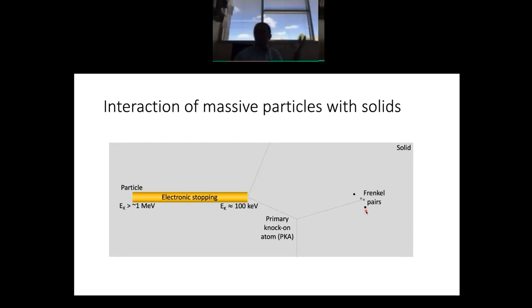And if I just think about what happens next, well, these things are just going to diffuse around, right? So they're just going to move around. Occasionally, you'll get a vacancy meeting up with an interstitial and recombining, annihilating. So that goes away. But not all of those vacancy interstitial pairs or Frenkel pairs are going to annihilate. Some of them are going to be left over. Those leftover vacancies and interstitials can diffuse around, interact with the microstructure. They are actually the source of radiation damage, right? So all the radiation damage that we study in the case of metallic alloys comes from these leftover vacancy and interstitial pairs that didn't annihilate, that are left over from this process of a particle interacting with a solid.